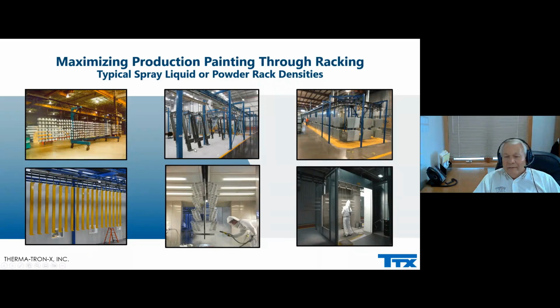it very well. The one on the right here is simplified, where you have one-sided, and you can do two parts per rack, double stacked, which gives them a single coat on one side. Same goes for this particular product. So you can see that the densities are that, and then when you look at liquid, sometimes it's even worse. And here, your densities are not as high.